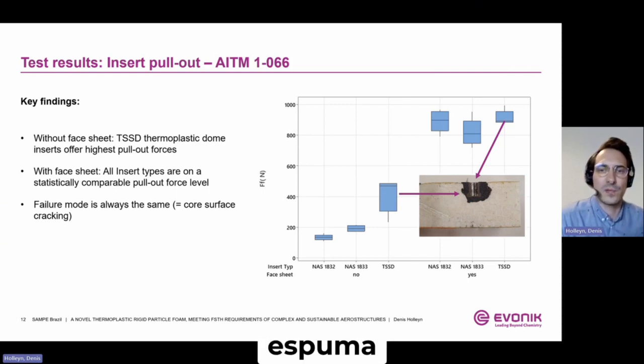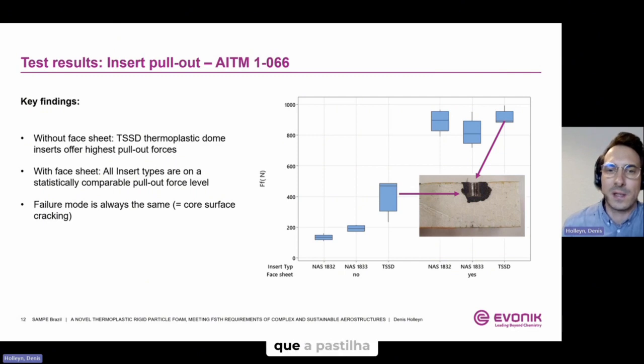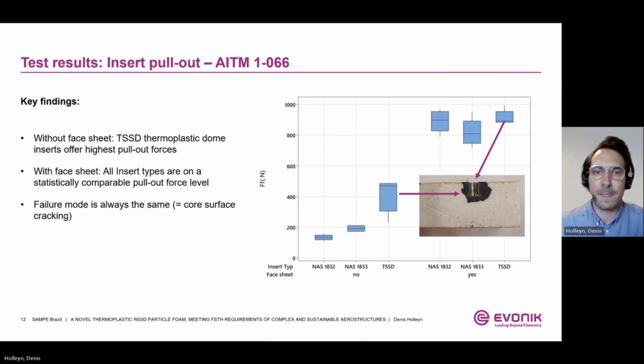The key findings, as you can see in the diagram on the right-hand side, are that the thermoplastic inserts lead to the highest pull-out forces when testing the pure foam without any face layer. The main reason behind this finding is the fact that the thermoplastic insert is drilled into the foam at high friction temperatures, which leads to a kind of welding of the insert dome to the thermoplastic foam.